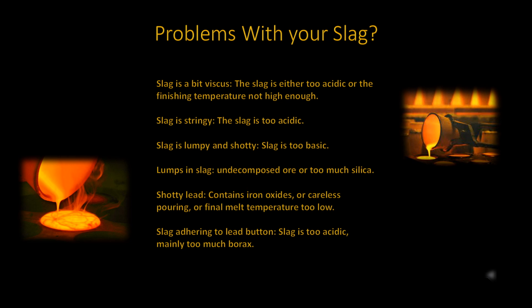As I have stated, the slag that you pour into your cone mold should be very fluid-like, low in viscosity, without lumps, etc. If your slag is a bit thick, meaning that it is more viscous than it should be, the temperature of the slag could be a bit on the low side. In this case, the temperature should be increased. However, if the charge was a little too acidic, the viscosity of the melt would increase. If this is the case, then the amount of silica and borax would have to be decreased, or an increase in the basic flux constituent in order to neutralize some of the acidity.